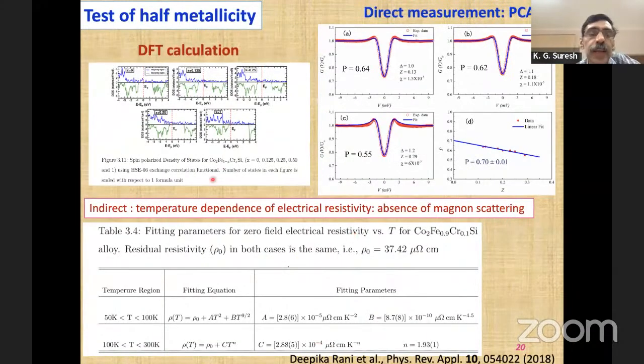So what is to be done? Of course, you can do a DFT calculation. It will tell you whether there is a gap. Of course, DFT alone cannot be relied upon. You need to have some kind of experimental proof. Experimental proof in the form of an indirect method can come from, for example, the temperature dependence of electrical resistivity. You know that there are different contributions, and different contributions have different temperature dependencies. And by careful analysis of the data or the fitting of these different temperature regimes, you can identify whether there are contributions which can give you information about the spin polarized aspects.